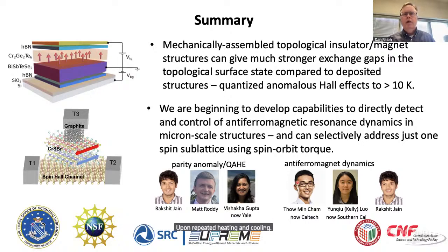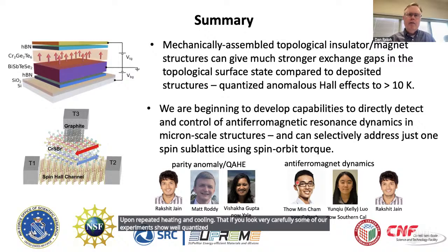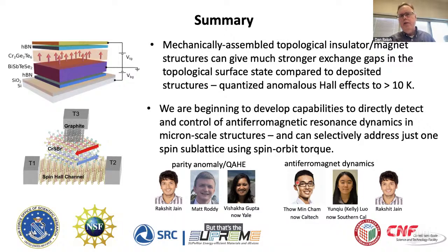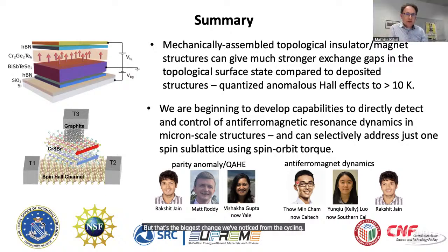Yeah, so we've noticed that the coercivity and the remnants change a little bit upon repeated heating and cooling. If you look very carefully, some of our experiments show a well quantized remnant state, and some of them begin to curve down a little bit once we get exactly to zero magnetic field. But that's the biggest change we've noticed from the cycling. We haven't noticed big changes in the exchange gap.